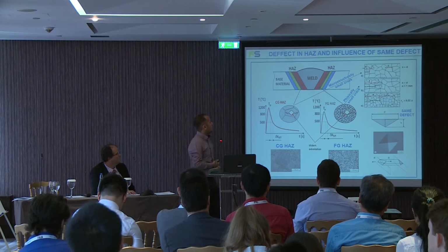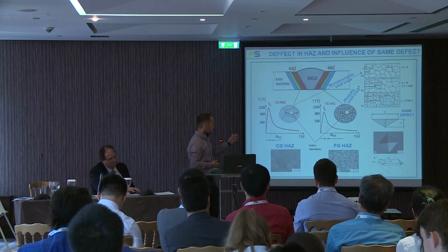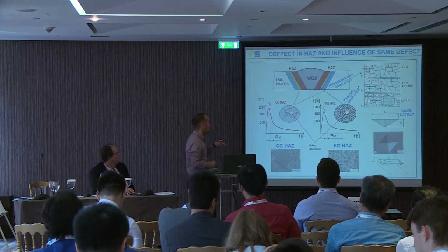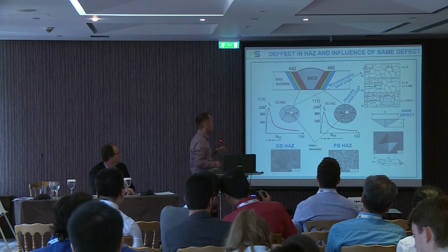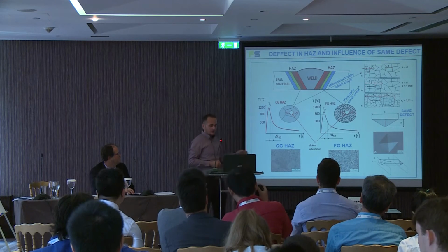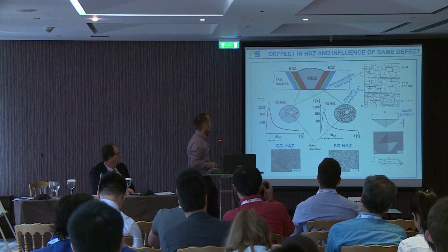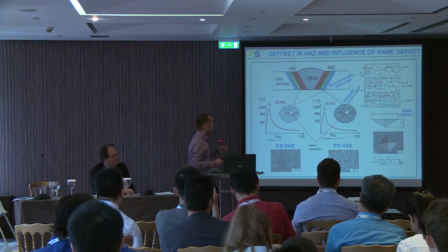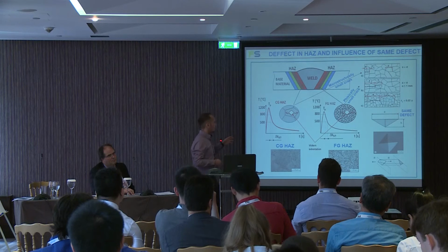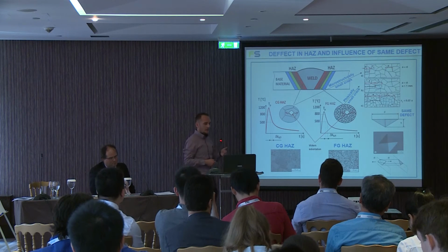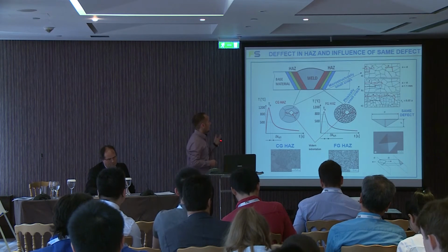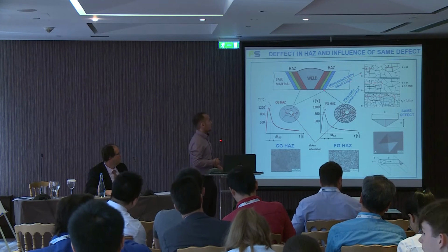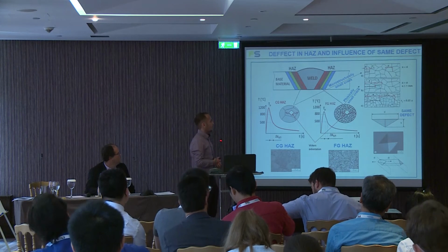And this is the defect which we made artificially in both microstructures. It is a Vickers indentation. In the first case, the grain was bigger than the size of the defect, and practically it is a microstructurally small crack.